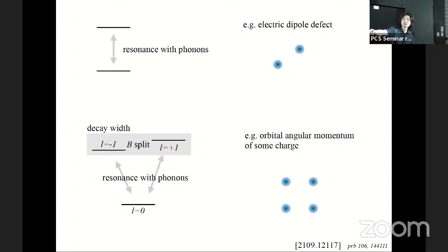And then the B split will be between the L equal to +1 and -1, right? And because they have different angular momentum, they should be able to keep track of the angle. And the interference between these two slightly different energies can generate this resonance skew scattering. So that's a kind of physical picture of the defect.